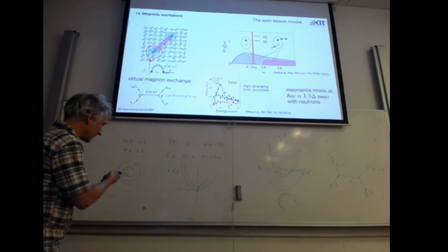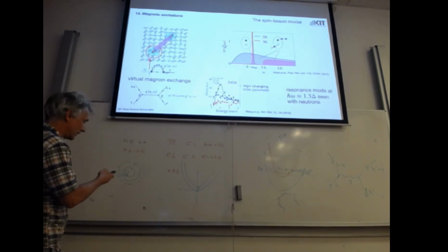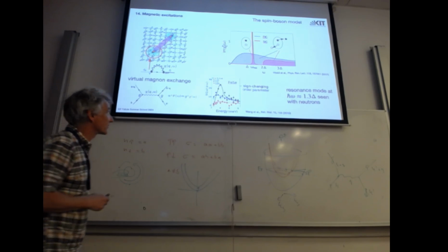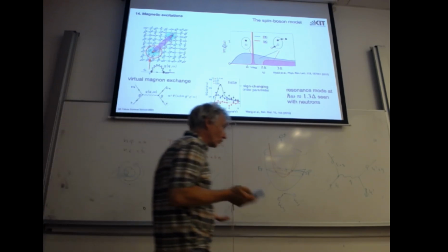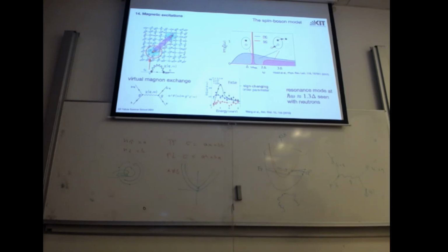And this is actually again the inelastic spectroscopy that we did before with magnets. Really the experiment we did on these antiferromagnetic layers. What will be the effect for superconductivity? That's a bit complicated now. If we are in a normal state, our magnons are very heavily damped. So we are in a paramagnetic ground state, we excite magnetic excitations for a short time, they will decay. So what we will get is a very broad spectrum.